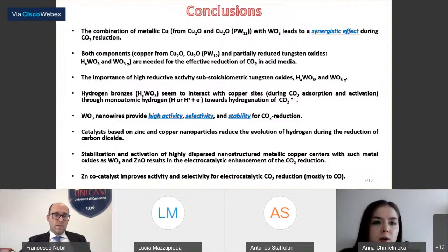Summarizing, the combination of metallic copper with tungsten oxide leads to synergistic effects during CO2 reduction. Both components are needed for the effective reduction of CO2 in acid media. Hydrogen bronze seems to interact with copper sites, moving from monatomic hydrogen towards hydrogenation of the anionic radical. Tungsten oxide nanowires provide high activity, selectivity, and stability for CO2 reduction. Catalysts based on zinc and copper nanoparticles reduce the evolution of hydrogen during the reduction of CO2.